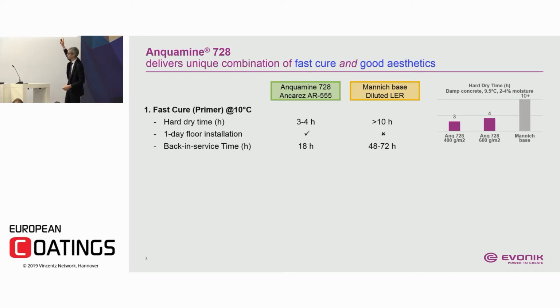The other thing displayed on the right hand side is that in the ANQUAMINE 728, whether you apply 400 or 500 or 600 grams, you get a cure speed of this 3 to 4 hours. So it's a rather robust system to work with. The water is gone after 3 to 4 hours, and you can apply your next coat.